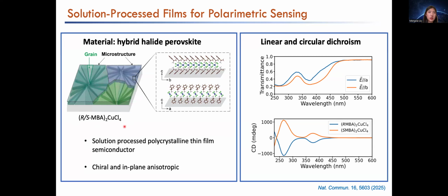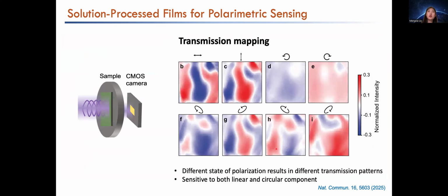Furthermore, we make this material with a chiral structure. So the material has a circular dichroism, which means it has differential absorption to different circularly polarized light as well. So with different circularly polarized light, the transmission of the material is also different. So this material fits all the required properties we are looking for. If we shine light onto this material with different incident polarization, we can get completely different transmission mapping.